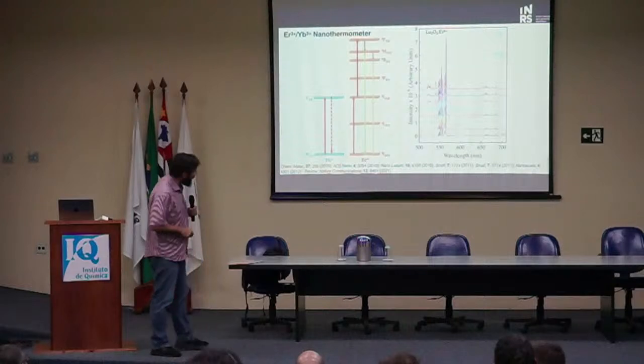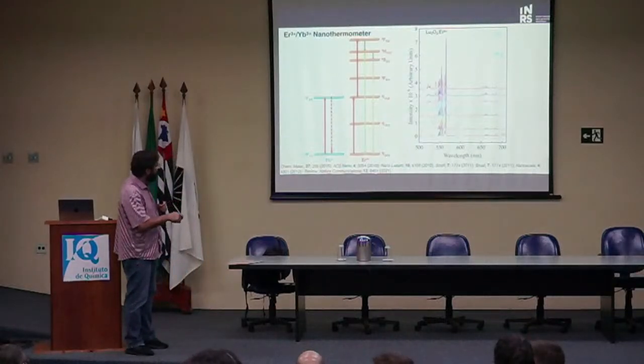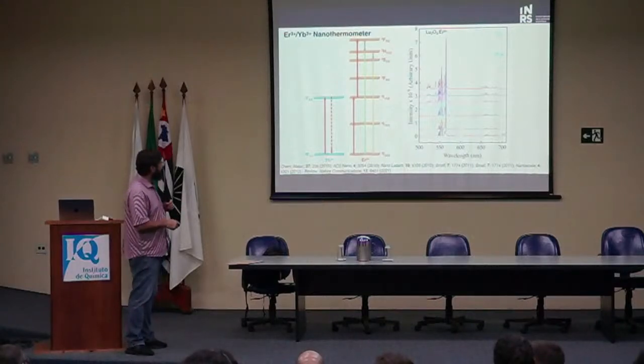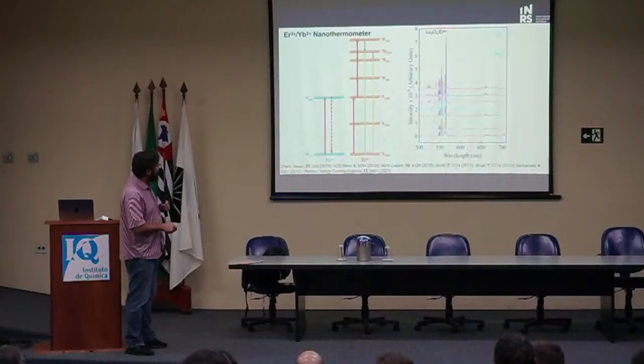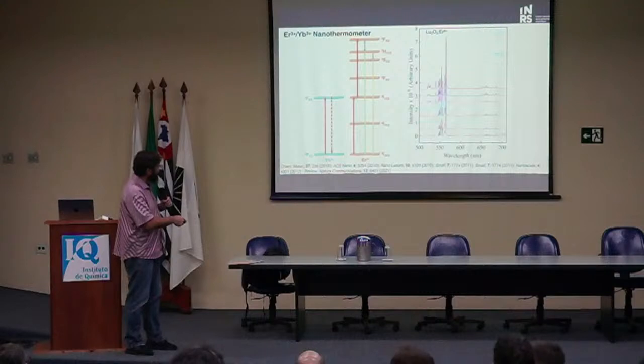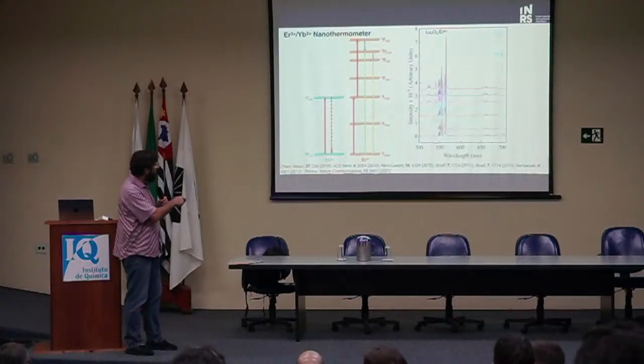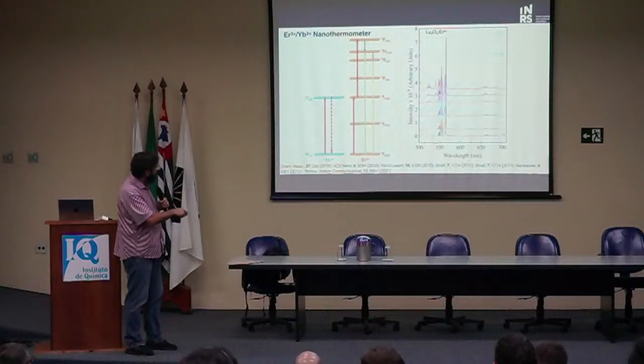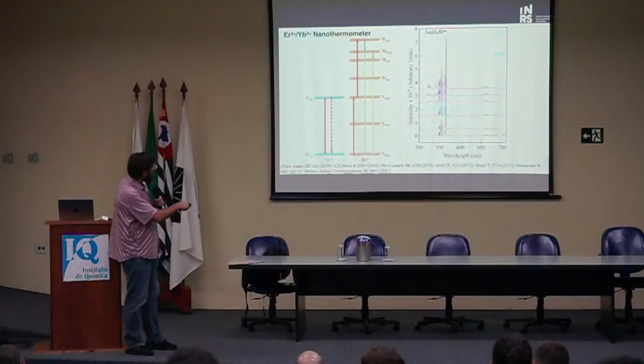Well, the classic ones are erbium, ytterbium. This was a figure out of my thesis from long ago, when we were working with the oxides, in this case lutetium oxide. We weren't doing thermometry back then, but we were studying the fundamental mechanisms of how we populate these excited states. If you look at these two emissions, this emission is from the 2H11/2 state. This big guy here is the emission from the 4S3/2 state. You have an upconversion process, or it can occur also if you excite at a higher energy, but regardless, you populate the state here. It will non-radiatively decay to the 2H state through multiphonon decay. Because these two states are really close in energy, this state will immediately non-radiatively decay to the 4S state, and we get this emission here.